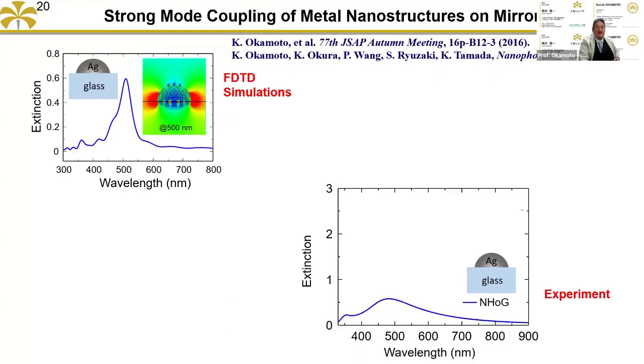First, we calculate with an FDTD electromagnetic simulation. If we put the silver hemisphere on the glass, in this case only one resonance peak is there. That's the dipole mode, and the quadrupole mode is also there. That's only one color. Right? That's the simulation. And in the experiment also, there's only one resonance peak and also a small quadrupole peak.